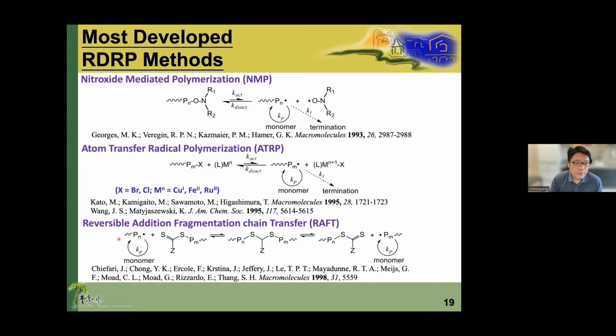Okay. Then RAFT polymerization actually uses totally another mechanism. RAFT polymerization uses the chain transfer mechanism, so there is an additional radical that attacks your chain transfer agent to kick out another radical. With this rapid exchange process, it can make all the chains have the same chance to grow. So these are the three most developed methods.